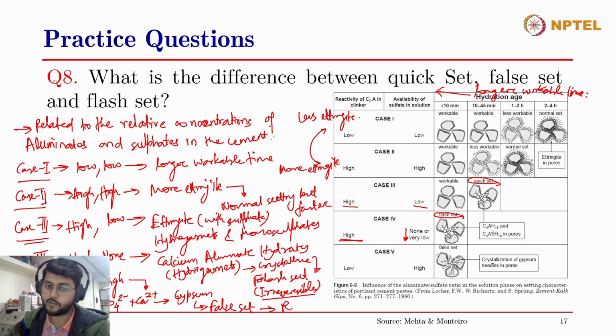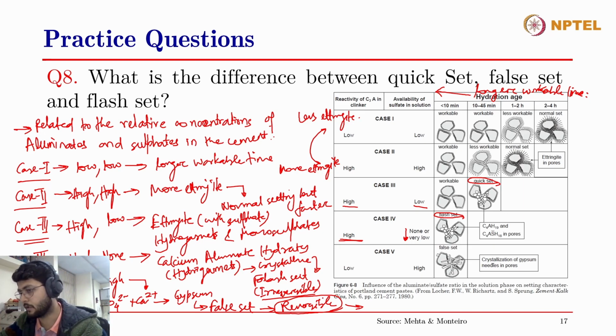This false set is however reversible, meaning that if you rapidly mix the cement again, then it will not set, and you can carry out the testing of the setting time. So it will first show a false set, meaning it will look like the cement is set, but if you continuously mix it for some time, then the precipitation of this gypsum and the network will be broken, and therefore you will be able to work with the cement and concrete. So this is called false set, right? This last case, false set. So this is the difference between the different types of setting phenomena that occur in cement.